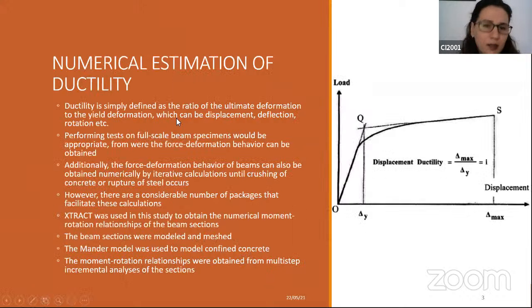So we know that ductility is the ratio of maximum to yield displacement, and normally ductility is obtained experimentally from testing full-scale members and obtaining their force displacement behaviors, and then doing this calculation. But there is a considerable amount of software that works on FE principles, which can also help to evaluate the force deformation relationships. We used one of these programs, Extract, to obtain the moment rotation relationships of the beam sections. We modeled and we measured these beam sections. It is an FE program for member sections. We used the Mander model to model confined concrete, and we used a strain hardening model for steel, and then we obtained the relationships that we wanted.